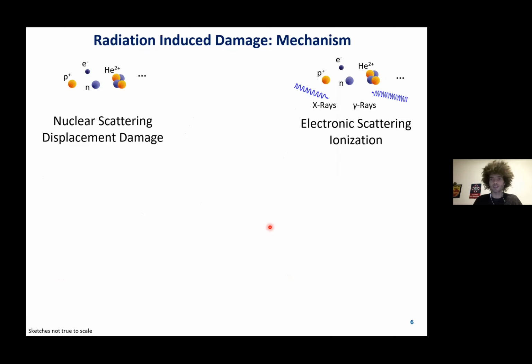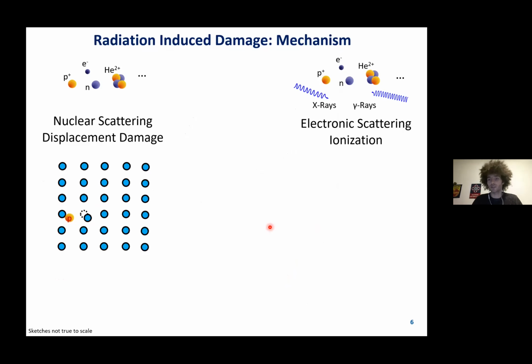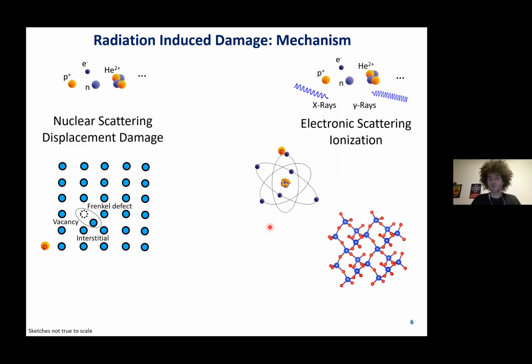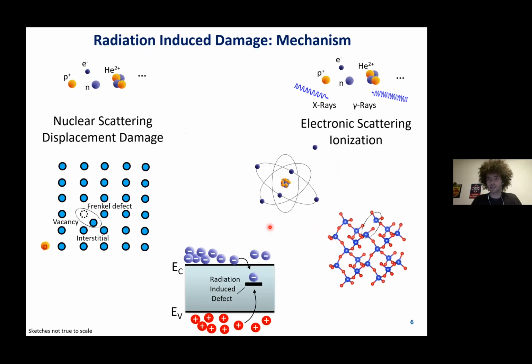The mechanism behind is basically nuclear scattering or displacement damage, in which, for example, a proton hits an atom in the lattice and then displaces this atom to an interstitial site. It can also be electronic scattering, in which a high energy particle ionizes and by this breaks any bonds in the material. So both effects lead to radiation-induced defects, which lead to additional non-radiative recombination. So I'm now trying to give some examples for different materials known from literature, basically.